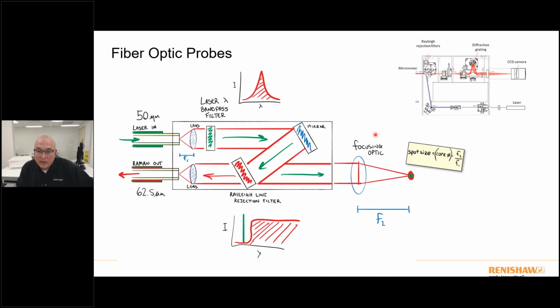And then you start to worry about spot size on your materials. So depending on exactly what your experiment is, you may want a small laser spot, or you may want a big laser spot. You may want a larger depth of focus, or you may want a tight depth of focus. So when I'm thinking about these things, I'm thinking about what is that core diameter, because I'm going to end up projecting the image of the core diameter onto my sample. So your spot size is no longer necessarily governed by the numerical aperture of your lenses, but more by the ratio of those focal lengths times the core diameter, so that if I have a 1-to-1 ratio in terms of these focal lengths, I'll end up getting a 50 micron laser spot on the sample.